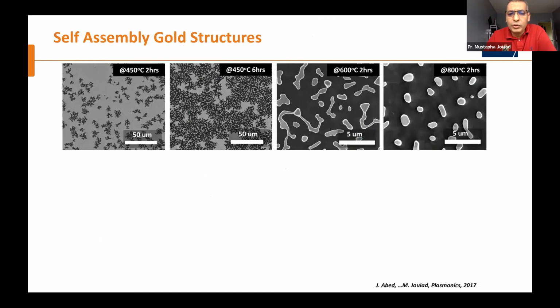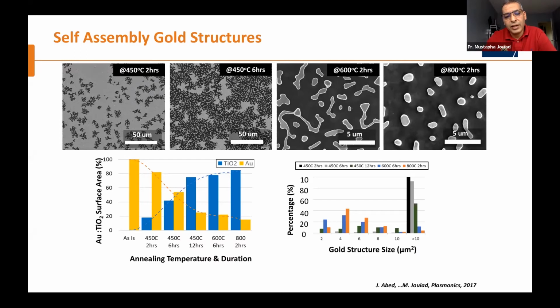To understand how it goes, we first prepared the neat material. Here is the first composite I showed you, many films, with gold on top, and we did different ultra rapid annealing, annealing only the top surface without touching the substrate. We were able to control the assembly of the gold nanoparticles. By doing this rapid annealing, we were able to increase the contact with titanium oxide while keeping the percentage of gold enough to make this interface very high. As we have nanoparticles, we have higher contact with titanium, better than having a film.